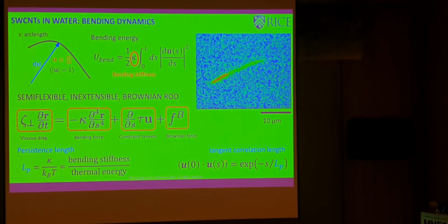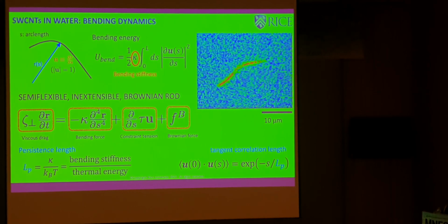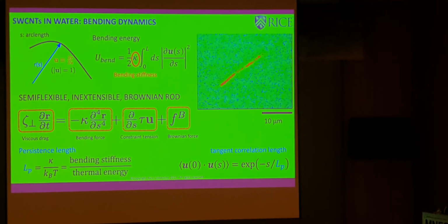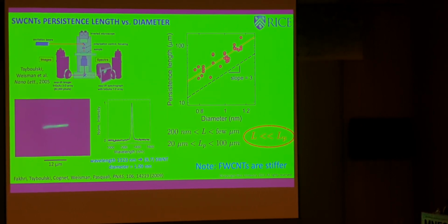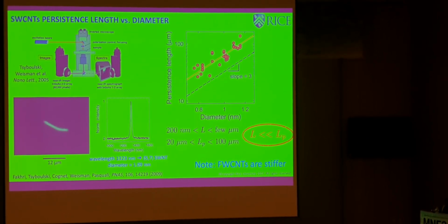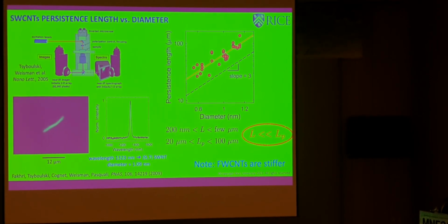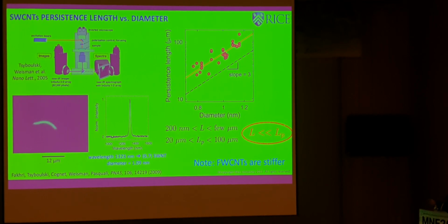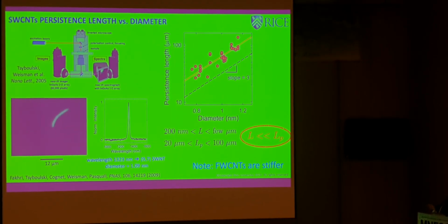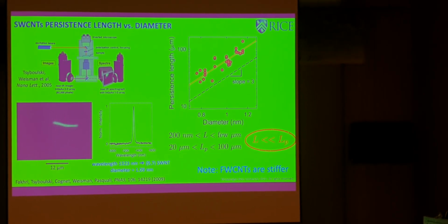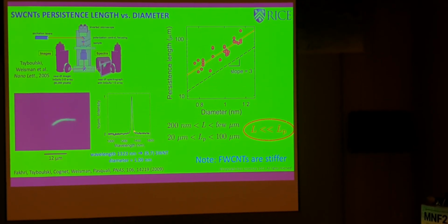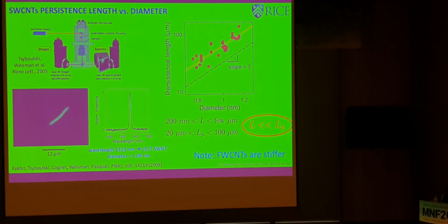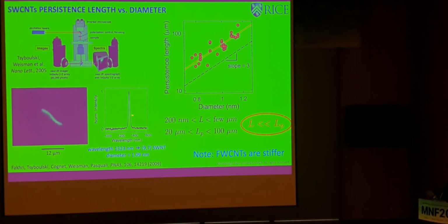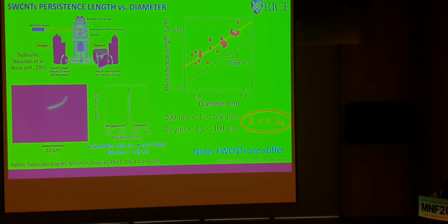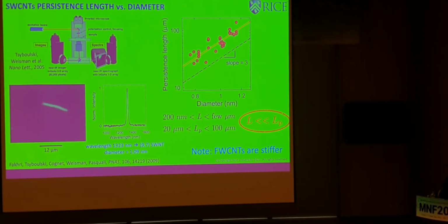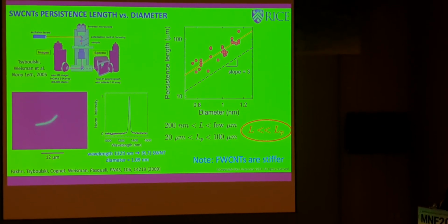And you can measure the persistence length by looking at the correlation length of a tangent along the contour length, right? And the cool trick about this was also that, of course, you expect this to depend on the diameter of the nanotubes, but the microscopy image does not give you the diameter. And so we worked with Bruce Weisman, who had developed a way to take the spectrum of an individual nanotube in a fluorescence microscope. And so we would take the spectrum and the images essentially at the same time. We just switch the beam to the spectrometer, get the spectrum, switch it back and get the images. And then by doing image analysis, we could get the amplitude of the bending modes, and from that, the persistence length.